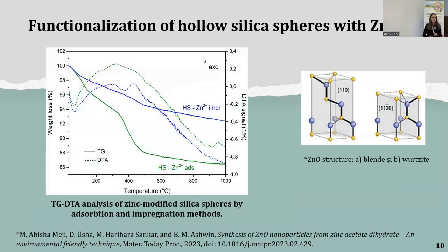Mesoporous silica spheres were modified with zinc oxide due to its well-known antibacterial properties. The method used was adsorption and impregnation using zinc acetate as a zinc source. Based on thermal analysis, the conditions of the thermal treatment for the decomposition of zinc precursor were chosen for both composite samples.